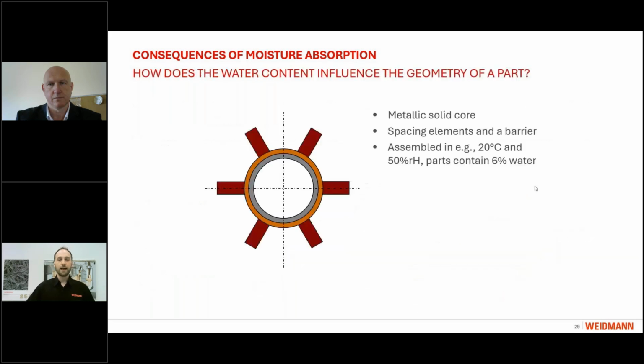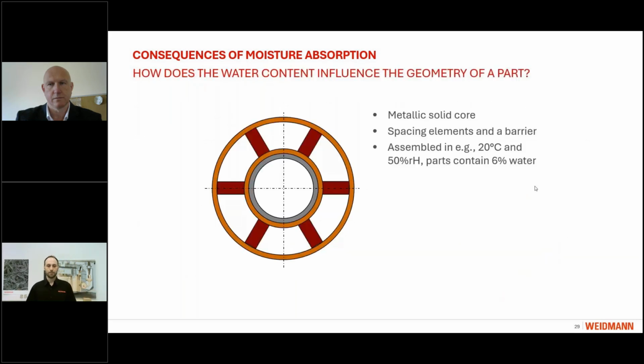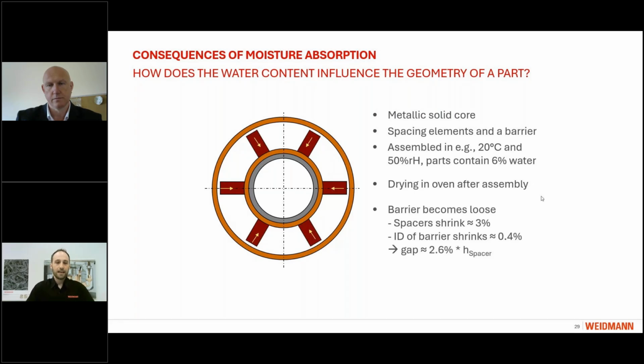Now, what happens if we have assembled a part at ambient conditions that are just normal, 20 degrees, 50% relative humidity, and that part was stored there for some time and gained 6% water content. Now we put it in the oven and dry it. And what happens is we have a shrinkage of the whole assembly, where the spacers shrink more than the inner diameter of the cylinder, generating a loose assembly. It is therefore critical to always know what we do and when and why and how to account for it.